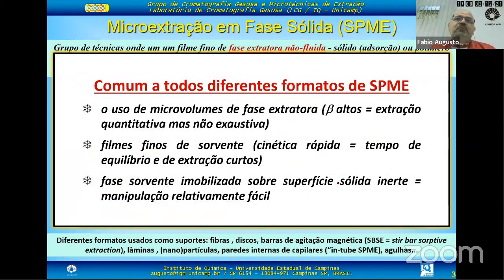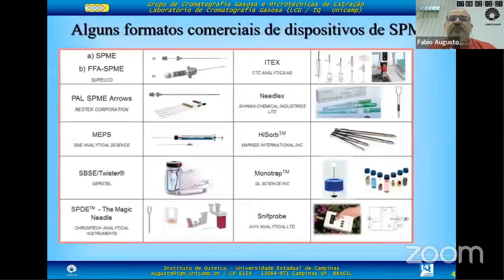Well, what is common to all those different formats of solid phase microextraction? Some are commercially available, others are only lab-made prototypes. They use microvolumes of extracting phase and high phase ratios, high ratios between the sample and extracting phase volume. You have a quantitative extraction, but non-exhaustive. They use thin films of sorbents, which means you usually have fast extractions, and the sorbent phase is immobilized over some surface. When you do that, you have very easy manipulation.